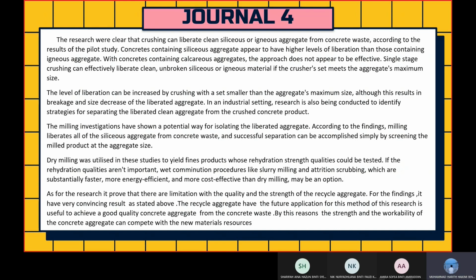According to the findings, milling liberates all of the siliceous aggregate from concrete waste, and successful separation can be accomplished simply by screening the milled product at the aggregate size. Dry milling was utilized in these studies to yield a fines product whose rehydration strength qualities could be tested, if the rehydration qualities aren't important. Wet comminution processes like slurry milling and attrition scrubbing, which are substantially faster, more energy efficient and more cost-effective than dry milling, may be an option.